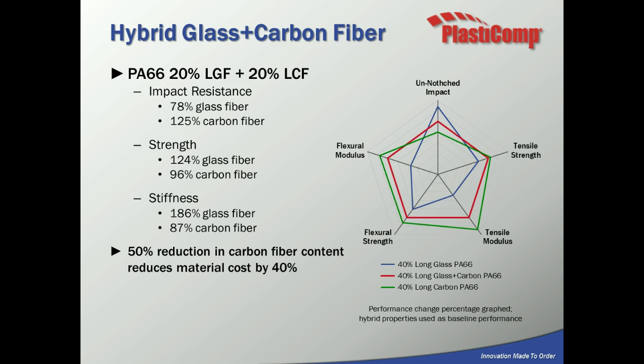This slide shows how a hybrid reinforced material compares to a long glass and a long carbon material. In this case, we're using a 20% long glass and 20% long carbon hybrid material. If you look over on the left at the impact resistance, when you compare that to a 40% glass material, we actually have 78% of the impact resistance, and we get a 125% performance boost over carbon fiber.